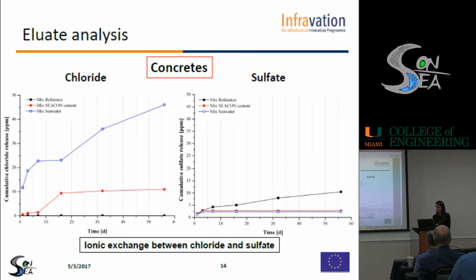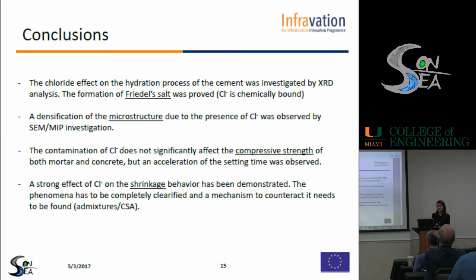Instead, for sulfate, this is different because we have to consider the possible ionic exchange between chloride and sulfate. So when chloride are released, sulfate aren't, and the opposite, when chloride are not released, sulfate are. In fact, mixed reference results in a higher release of sulfate because probably they are not bound as in the other 2 cases.